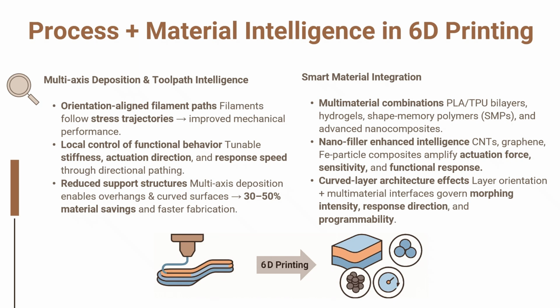On the process side, multi-axis deposition gives us unprecedented control of filament orientation. We can align extrusion paths with stress trajectories, which significantly improves mechanical performance compared to planar layering. This also means we can locally tune stiffness, actuation direction, and response speed simply by adjusting the orientation of the toolpath. Another major benefit is the reduction of support material. Because we can print on curved surfaces and in multiple orientations, we eliminate many of the support structures required in 3D printing, leading to 30 to 50% material saving and faster fabrication.